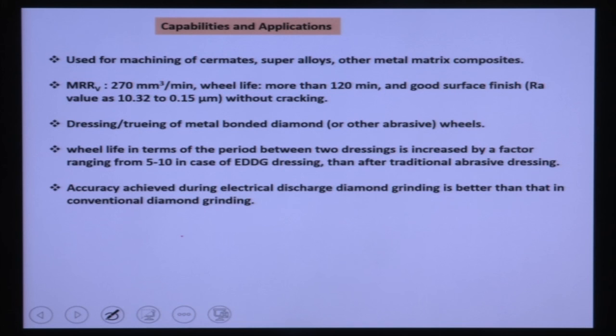Capabilities and applications: it is used for machining of ceramics, superalloys, and other metal matrix composites. The metal removal rate in electro-discharge diamond grinding is very high. It is 270 cubic millimeters per minute. Wheel life is 120 minutes. Wheel life means the time between successive dressing operations, so it is 120 minutes. And good surface finish is achieved, from very high values down to 0.15 micron depending on your applications, without any cracks.